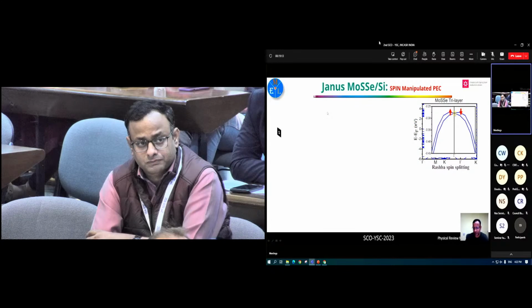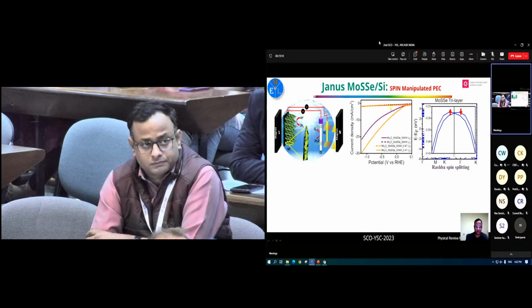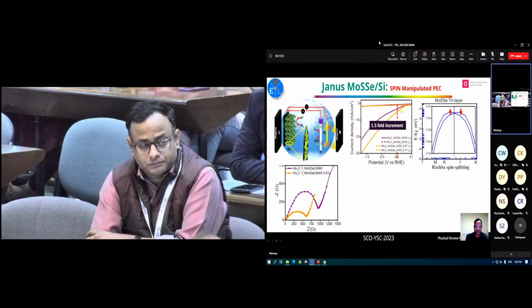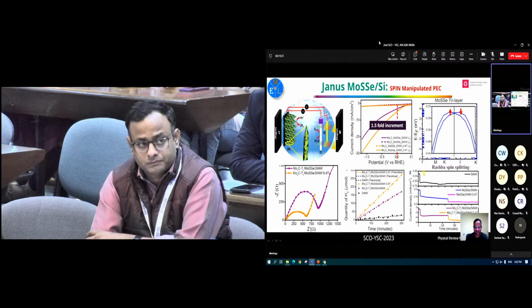It shows the Rashba type of splitting in MoSSe, and when you do the water splitting experiment as a cathode, you can see a 1.5 fold increment under the magnetic field. It's 0.4 Tesla, a very small magnetic field. Then we tried to understand what is happening, because MoSSe doesn't have any magnetic element, but still under the magnetic field it shows the increment. It shows lower charge resistance under the magnetic field, and also the overall performance increases. So we have done other physical property, magnetic measurements, and MCD experiments.